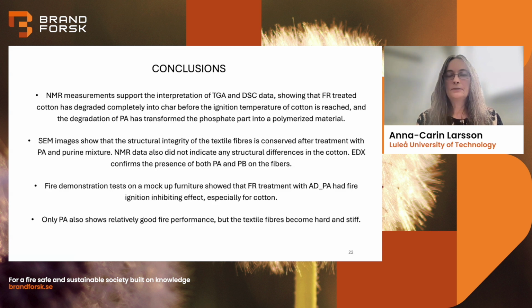The fire demonstration tests on a mock-up furniture show that the flame retardant treatment with adenine and PA had a fire ignition inhibiting effect, especially for cotton. We could also see that if we use only PA, we also have a relatively good fire performance, but the textile fibers become hard and stiff. So the addition of this purine base improves the quality of the material itself.